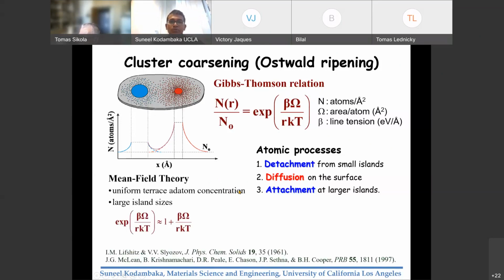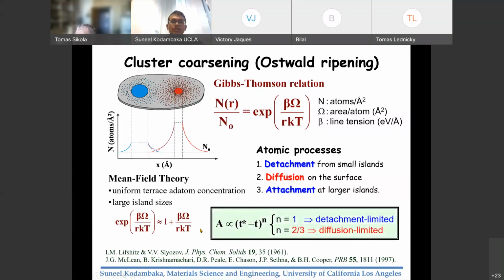and that was done a long time ago by Lifshitz and Slyozov, who came up with the mean field theory model, where assuming that the atom concentration on the surface is uniform, and assuming that the clusters are all circular, and if the clusters are large enough, the exponential could be expressed in terms of the first 2 linear terms, using which they were able to identify how the area of a given cluster would change with time. And the scaling exponent associated with this behavior is indicative of the mechanism that controls this process.